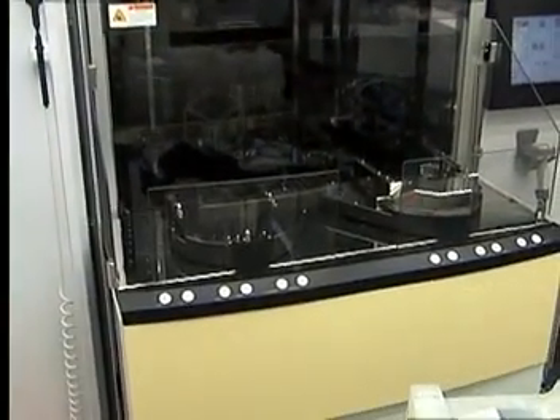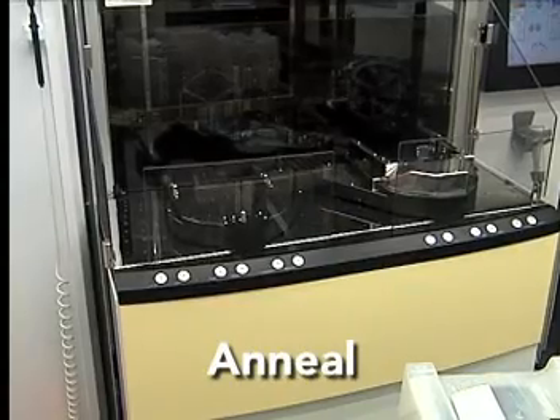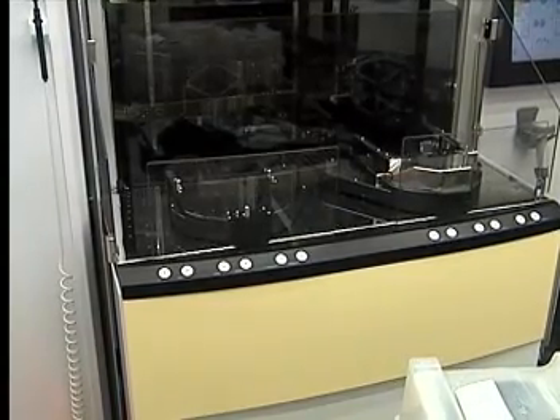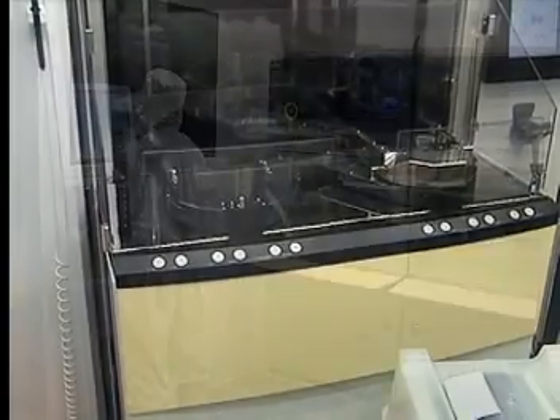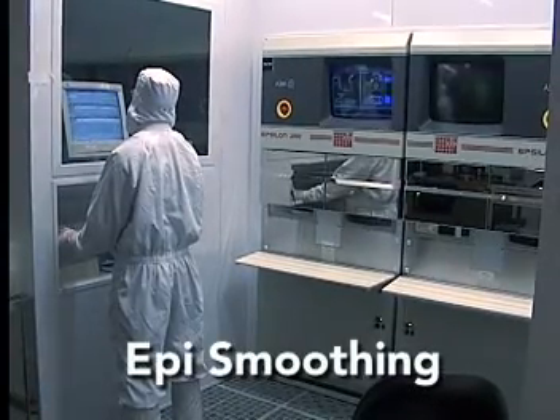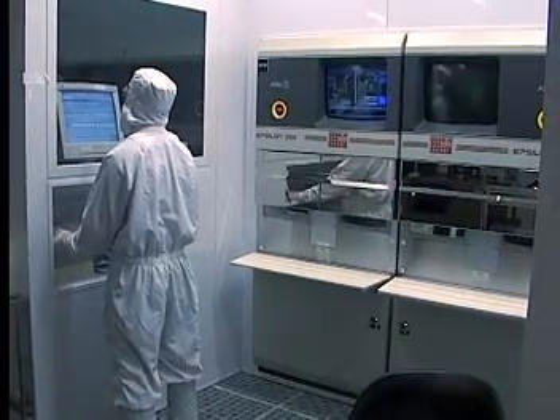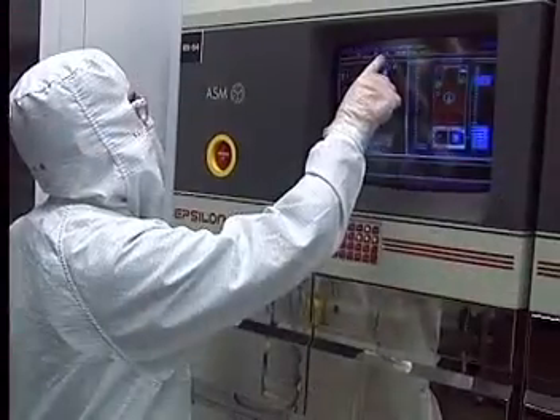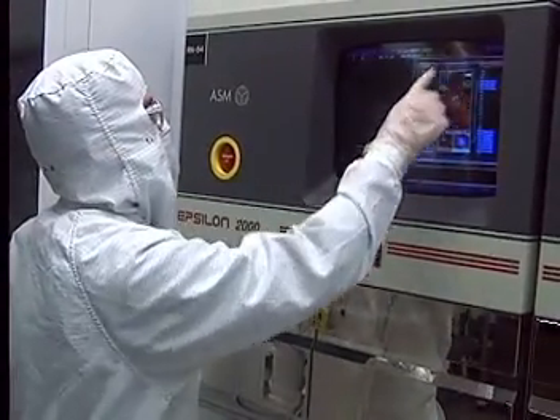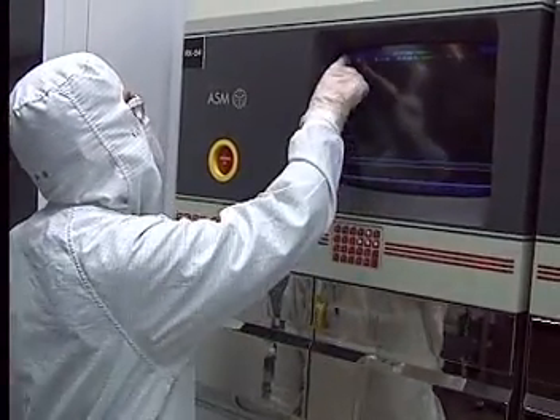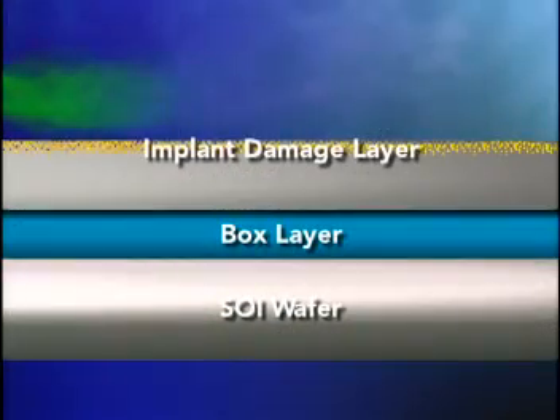The as-cleaved SOI wafer is next given a high-temperature anneal to produce a high-quality bond interface. After this step, the SOI wafer is ready for the epi-smoothing process. The proprietary epi-smoothing process is a high-temperature gas phase silicon etch performed in a single wafer epi reactor. The epi-smoothing process etches away the residual implant damage from the surface of the wafer.